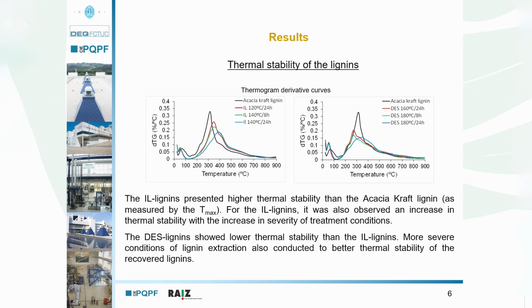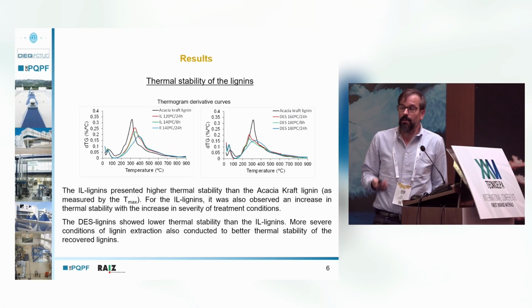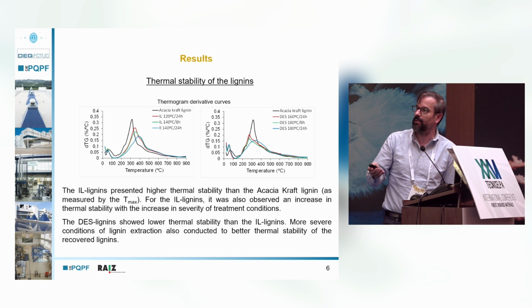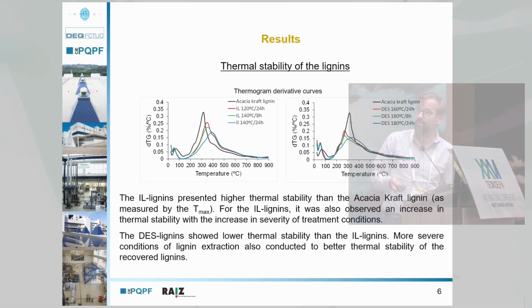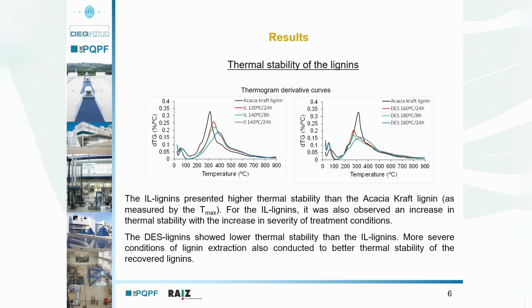How did we obtain this lignin? We performed a cooking of Acacia dealbata up to a kappa number of around 16, and from the black liquor of this Kraft cooking of acacia, we obtained lignin by precipitation with acid. So this is our reference, the acacia Kraft lignin, and as I will show later, it can also be a good approach for the valorization of lignin. But returning to thermal stability, you can see that the lignins obtained by extraction with ionic liquid present higher thermal stability than the acacia Kraft lignin. The acacia Kraft lignin was obtained from the same wood sample, but based on the Kraft cooking process.